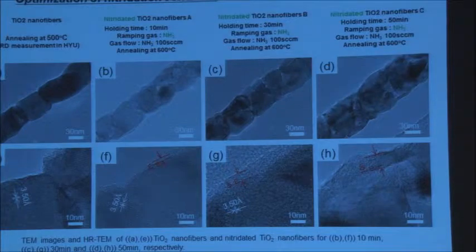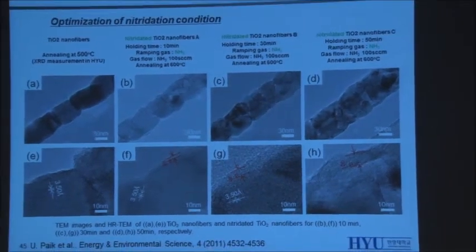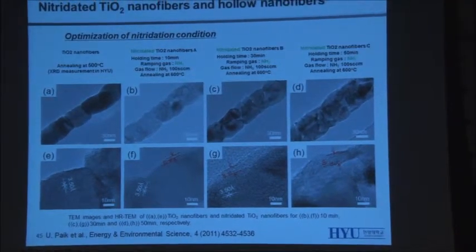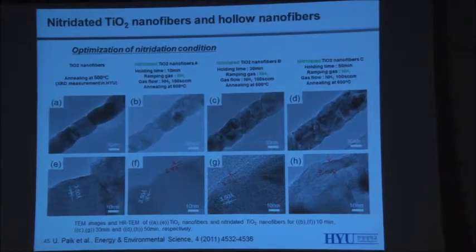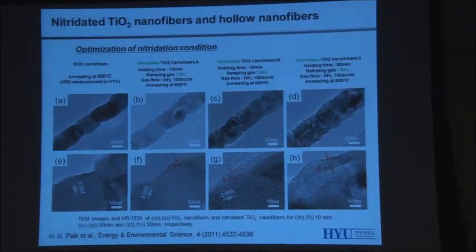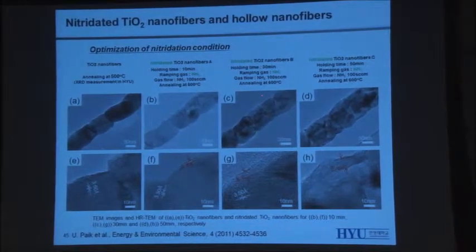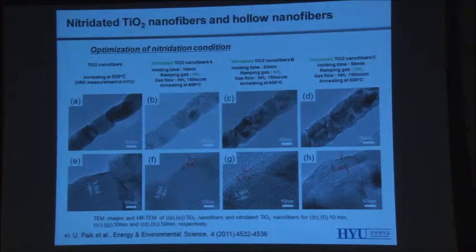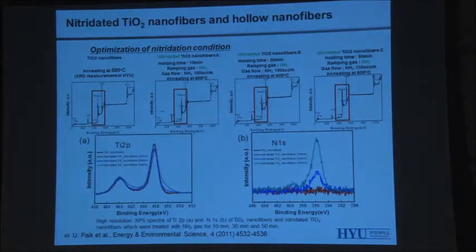So we have carried out many experimental conditions to optimize the titanium nitride thickness. So a holding time of around 30 minutes at 600 degrees shows the best thickness of titanium nitride, which yields the best rate capabilities.